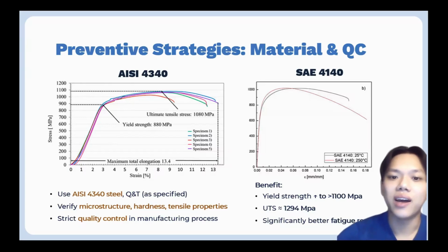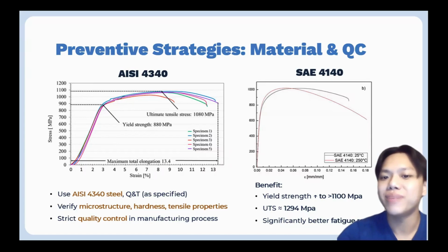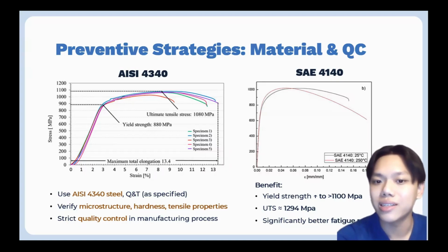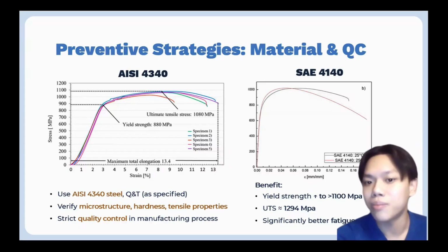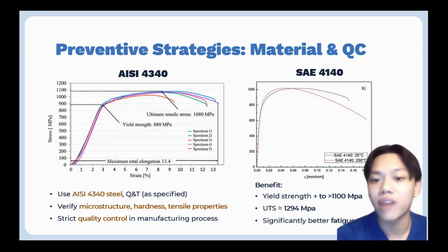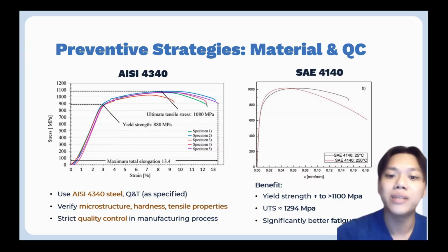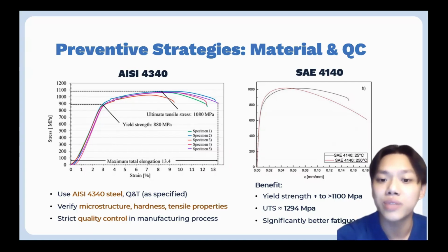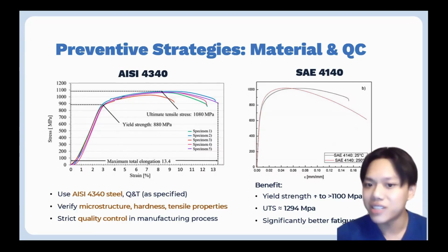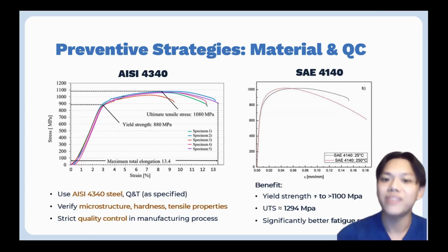Okay, now the first and most important preventive measure is strict compliance with specified materials and heat treatment. The shaft should be made from AISI 4340 steel in quench and tempered condition, as originally designed. To ensure this, routine checks of microstructure, hardness, and tensile properties should be carried out as part of a rigorous quality control process. If this had been done, the yield strength would have been raised above 1100 MPa and the ultimate strength to nearly 1300 MPa, providing a much larger safety margin and significantly improving the fatigue resistance of the shaft.